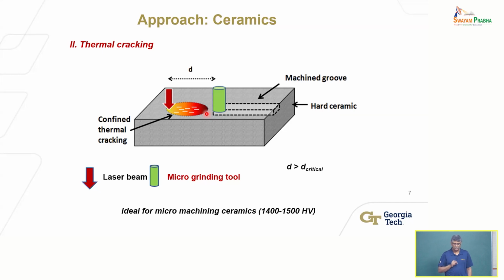Okay, so you essentially shock the material by exposing it to a laser, again, some distance in front of the tool. And that laser-matter interaction, in this case with the ceramic, what will heat do? It's going to cause local expansion. Well, ceramics are not very good in tension. They can handle compression, but they're not very good in tension. So the idea is if you apply enough thermal stresses to the material such that you exceed the fracture strength of that material locally, then you will generate cracks and you will weaken the material.